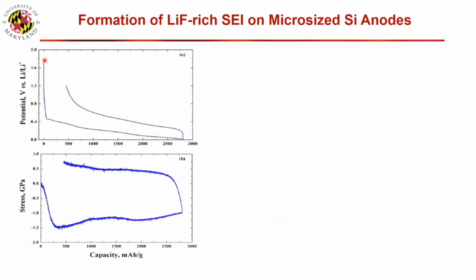And then we think the mechanism is this. This is a charge-discharge curve for silicon, and this is the stress measured using a thin film of silicon. The concept is that during lithiation and the volume change, you see elastic deformation at the beginning, but after a certain lithiation level it becomes plastic. Meaning that with lithium at high concentration, the silicon is really soft. So if we can block with the SEI during the elastic deformation, so that electrolyte cannot penetrate later, even if they crack, they can self-heal because they really flow. So we think the opportunity is that when we decrease the potential, meaning at initiation, at the beginning when it reaches a potential lower than that of PF6, it forms lithium fluoride.